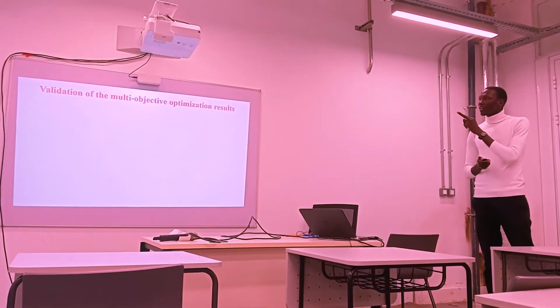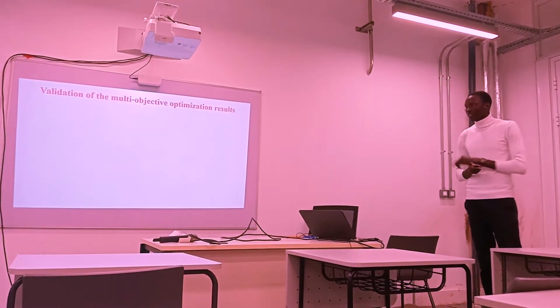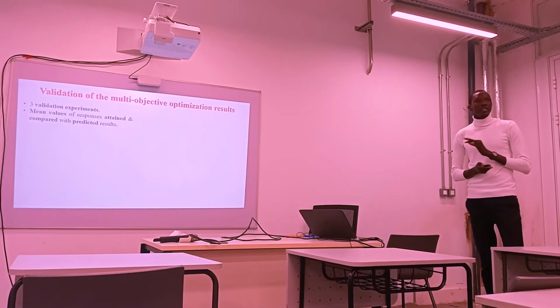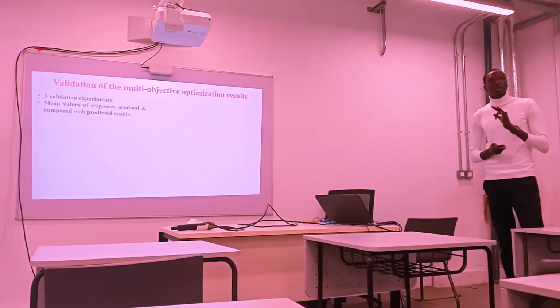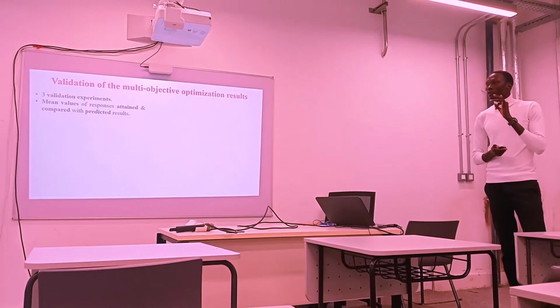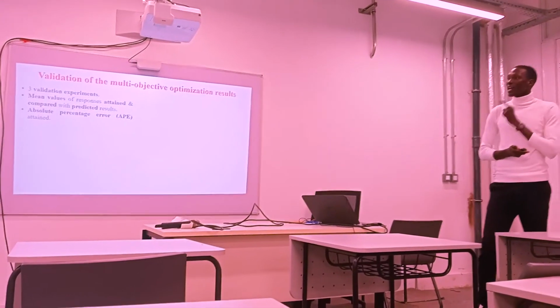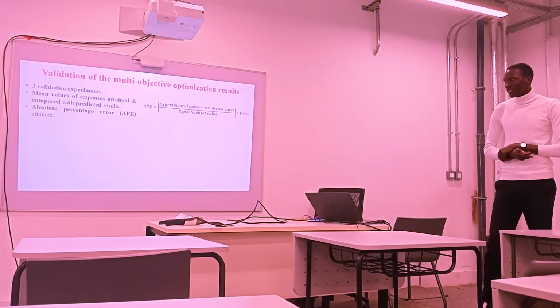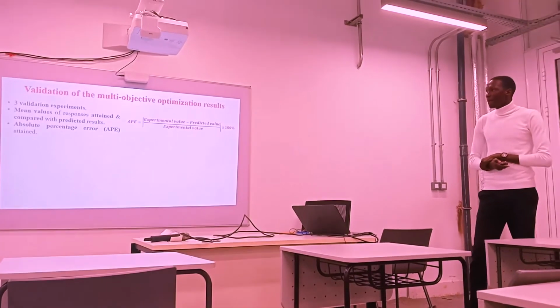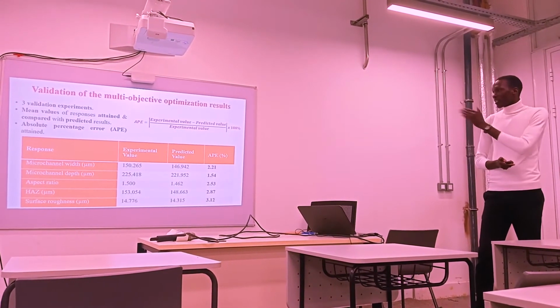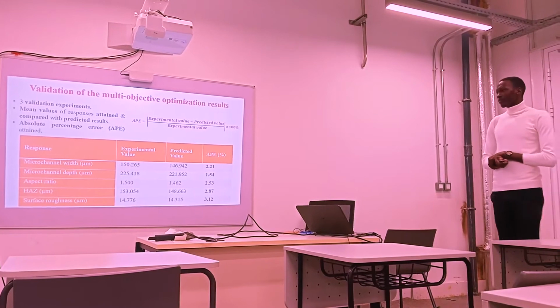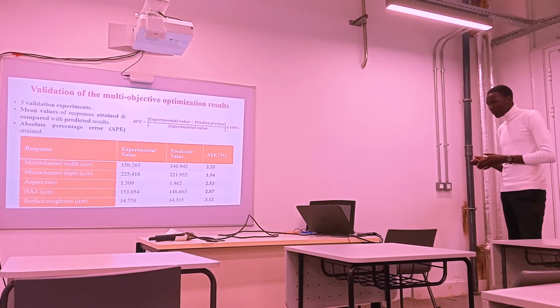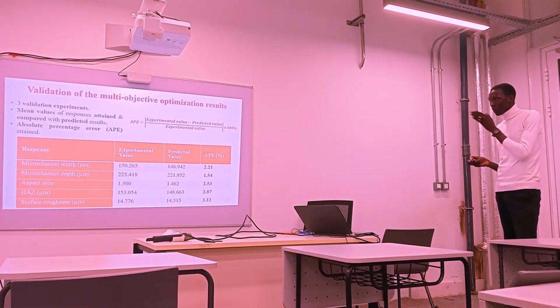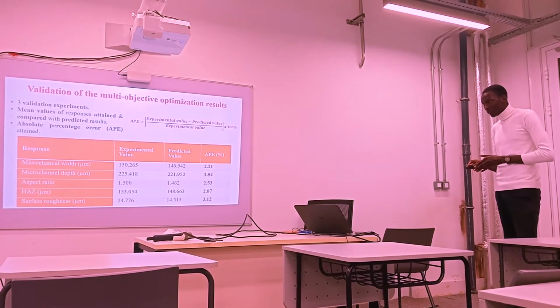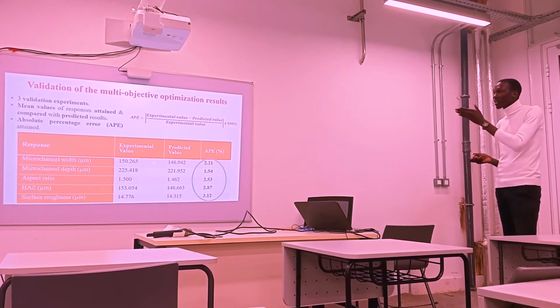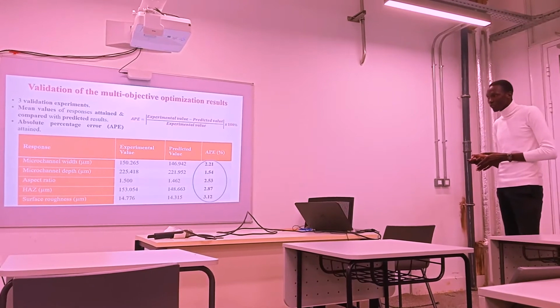Then we validated the multi-objective optimization results using 3 sets of experiments. And then we got the mean value of the responses. And then we calculated the absolute percentage error using this equation. These are the results we got. As we can see, the values of absolute percentage error are very small, because the experimental values are close to the predicted values.